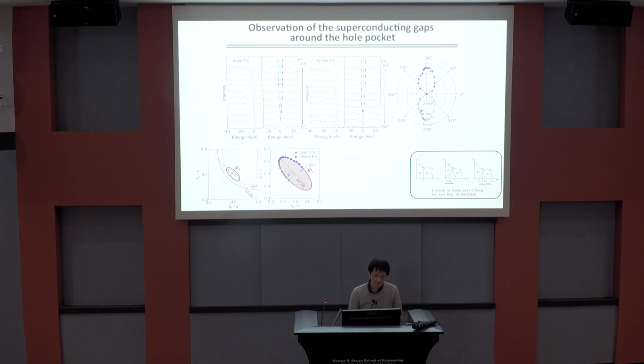So this gap opening in the pocket means superconducting pairing and antiferro order coexist with each other. Before, there was an argument about which phase is correct: a clear separation between antiferro and superconductivity, or a uniform mixture between these states. Some people think the inhomogeneous state observed by STM may be due to this separation and slight gap difference for each domain in real space. But our result means pairing can really uniformly coexist with this antiferro order.